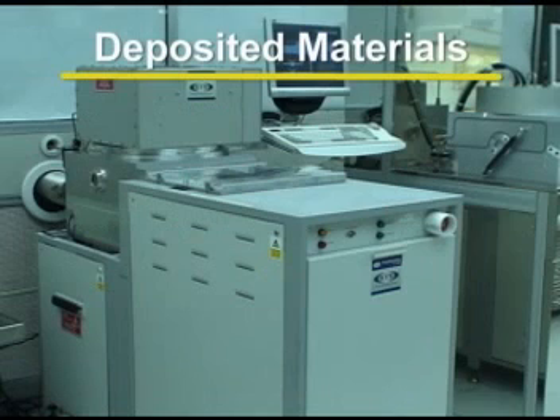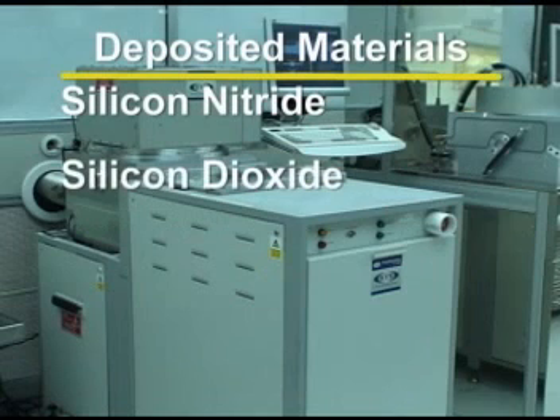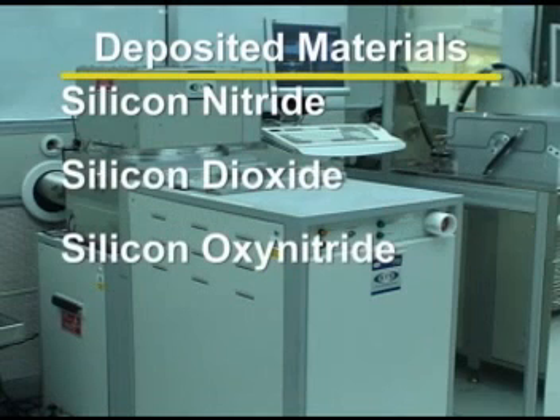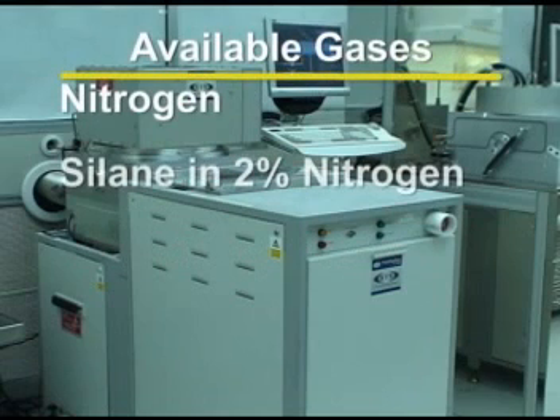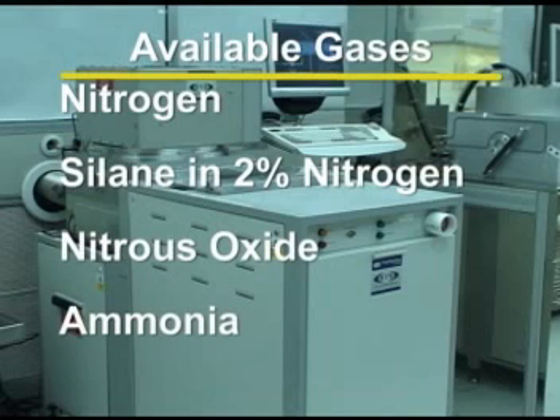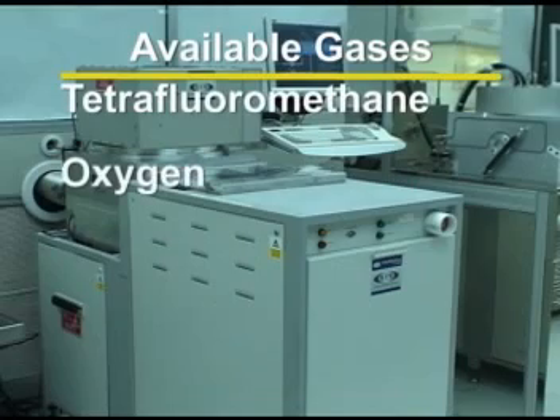Here at the MRC, the STS PECVD is primarily used for depositing silicon nitride, silicon dioxide, and silicon oxynitride. The list of gases available for processing includes nitrogen, silane in a 2% nitrogen mixture, nitrous oxide, and ammonia. The gases available for cleaning the chamber are tetrafluoromethane and oxygen. Let's now introduce our lab users.